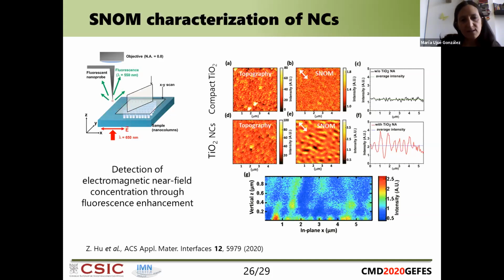So what we did was to scan on top of the flat area, the compact titania. This will be just the topography. And as you see, the SNOM signal is very homogeneous. The intensity is flat, and this is the average.